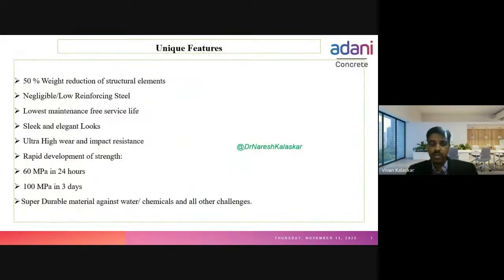Unique features, as I've told, with UHPC we can reduce the overall weight of the structure, with negligible low reinforcement steel, low maintenance cost, sleek and elegant looks, and ultra high wear and impact resistance. And within 24 hours, we can reach up to 60 MPa compressive strength. Within 3 days, we can reach up to 100 MPa compressive strength.